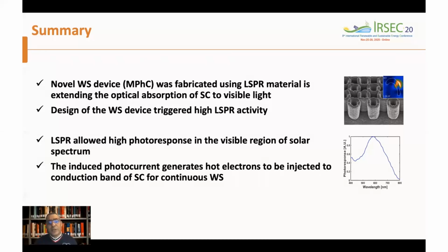We also showed that this LSPR has a very high Q factor compared to what is reported in the literature, and the induced photocurrent will provide hot electrons to be injected into the conduction band of the semiconductor, allowing continuous water splitting.